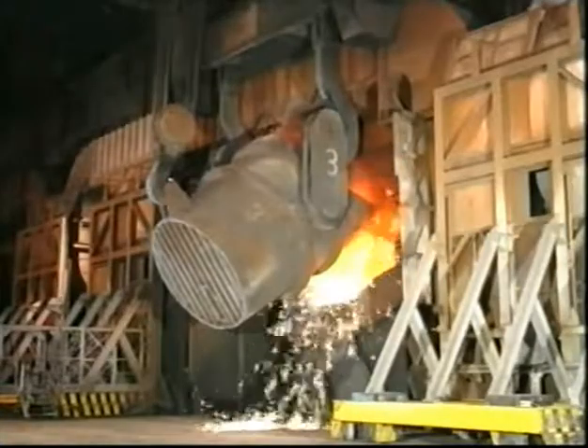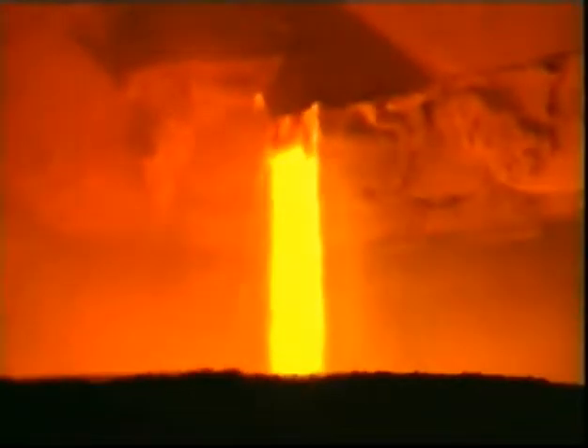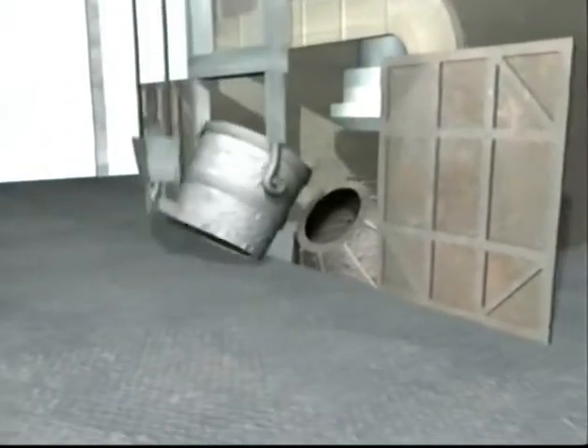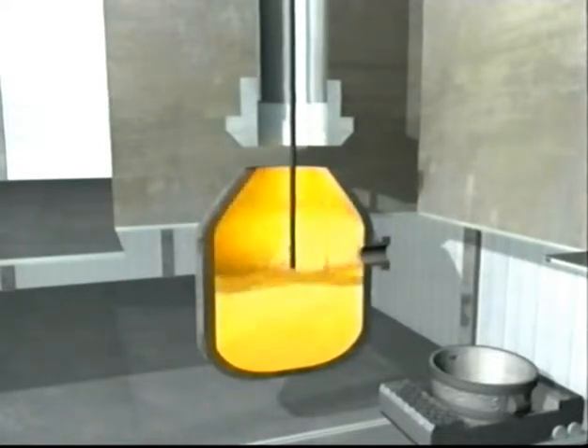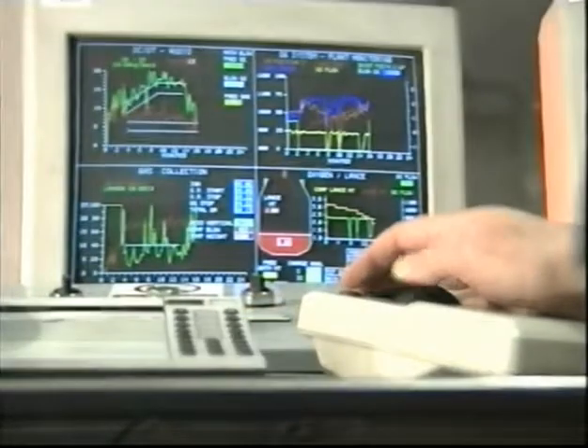Basic oxygen steelmaking, or BOS, is the main bulk production process for refining iron into steel. BOS vessels can take up to 350 tonnes of molten iron at a time and convert it into steel in less than 30 minutes. First, scrap steel is put into the vessel, and then the hot metal is added, which may have been pre-treated to remove elements such as sulphur. A lance then blows high purity oxygen onto the hot metal at about twice the speed of sound. The oxygen combines with impurities and this oxidation produces heat. The temperature is controlled by the quantity of scrap steel and also by the addition of iron ore as a coolant.